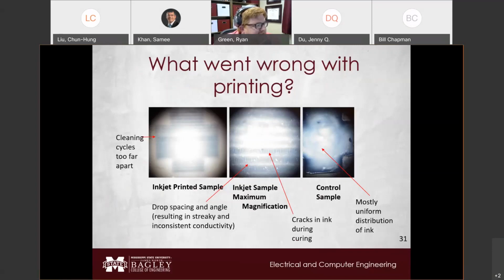What we find is that there's a spacing in between the drops with your inkjet printer, which results in this streaky device that's not really consistent in terms of deposition or even conductivity. And then on top of that, you have cracks in it. But as opposed to our screen printed, which is mostly uniform, has a better result. So ultimately, we're going to have to go back to the drawing board when it comes to setting our printer properties for this. But it's still promising that we can do this even with the screen printing technology. And the great thing about screen printed technology is now you can produce things on more flexible substrates, which makes it a little bit easier for deployment.